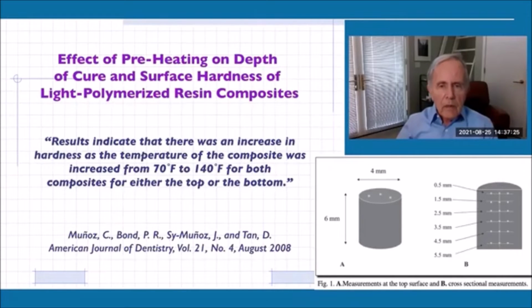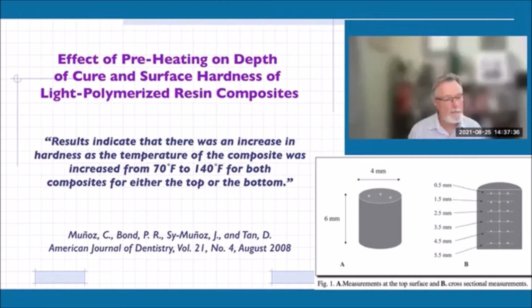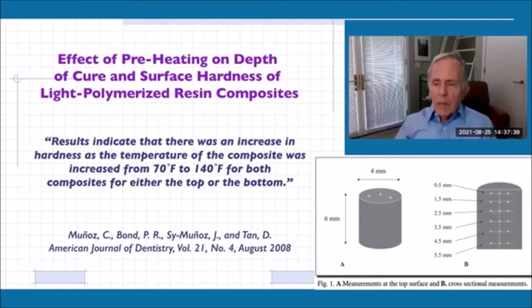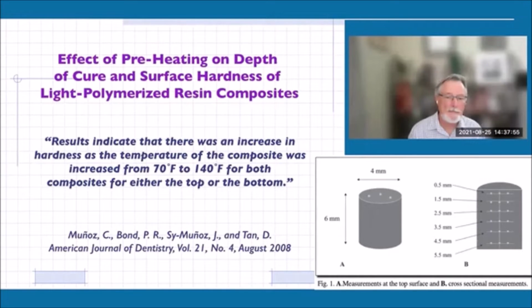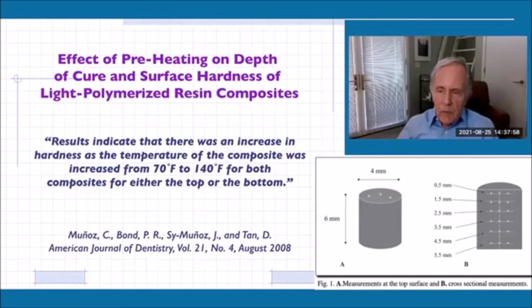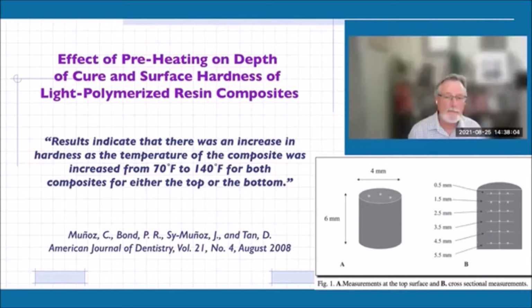One way to get the depth of cure is to measure the amount of hardness at different depths. So in the right-hand corner, we see a sample that's 6 millimeters in depth. And what they do with this is they cure from the top, but then they measure the hardness at these different levels, 1.5, 2.5, et cetera, down to 5.5 millimeters. You know that the composites are going to be hard at the surface. It's easy to test, but you don't really know what's happening at the bottom, and that's the critical part. So by doing this kind of a test, they split this sample in half, and they can take hardness measurements of the sample at different depths.